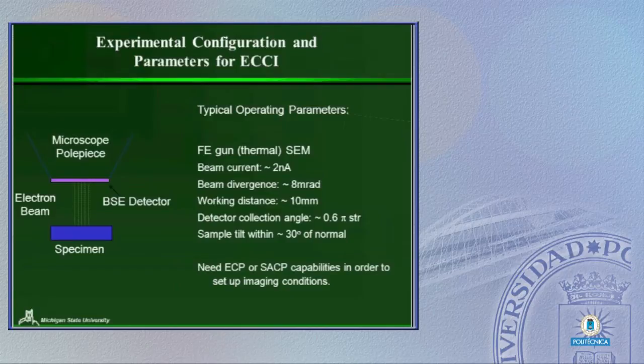What we do, and I'll discuss a little bit more, but we generally use the specimen pretty much perpendicular to the incoming electron beam. We can tilt it about plus or minus 30 degrees and still be able to use this fairly usefully. But this is a different configuration than a couple of other people use.